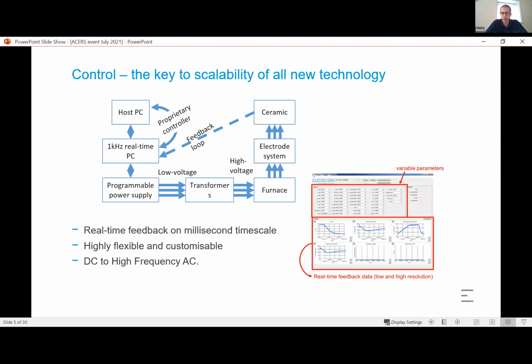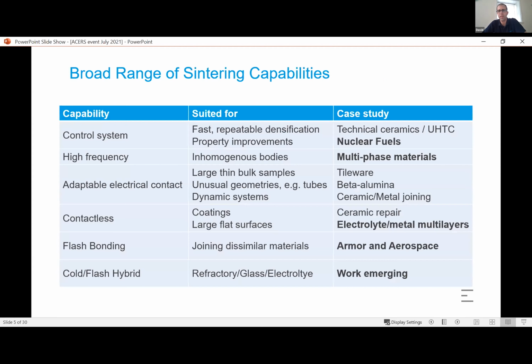So I mentioned quickly, I won't spend long on this, but we've got a development software piece, and this really monitors. It's a non-linear real-time control software. So it reacts with our application of the field to the ceramic and can adjust in milliseconds so that we don't have any of these defect hotspots formed by the process, and we can operate over larger surface areas. We're very customizable. It's a materials dependent process, so it needs to be optimized for each of these materials and geometries and scales. We do DC all the way through to high frequency AC, and there's some interesting effects there.